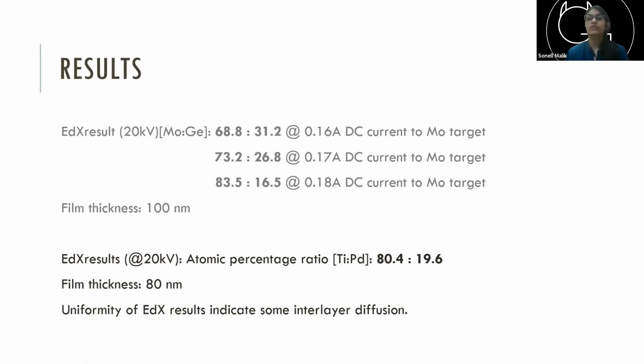And for titanium and palladium, I deposited alternate layers. So to figure out if there has indeed been mixing, you take your EDX samples from multiple places on your sample. You can't do an EDX for the whole 1 centimeter by 1 centimeter sample, because you need to be very specific in your region. If you pick different regions from your sample, then you can figure out if there is uniformity of the concentration. If there is uniformity, that means there is significant diffusion on your chip, which is good, which means you will have an alloy instead of just alternate layers of titanium and palladium.